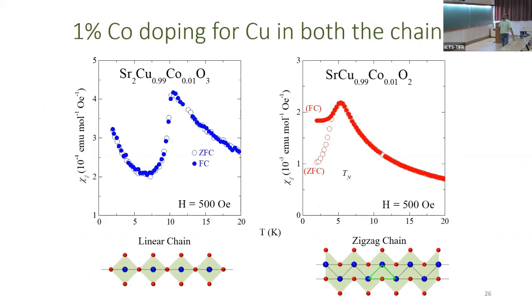But what you see here is that in the case of the linear chain, where there's no frustration, the zero field cool and field cool data completely overlap. On the other hand, in the case of the zigzag chain, where there's frustration, the zero field cool and field cool separate out. So there's a thermomagnetic irreversibility, which is a sign of